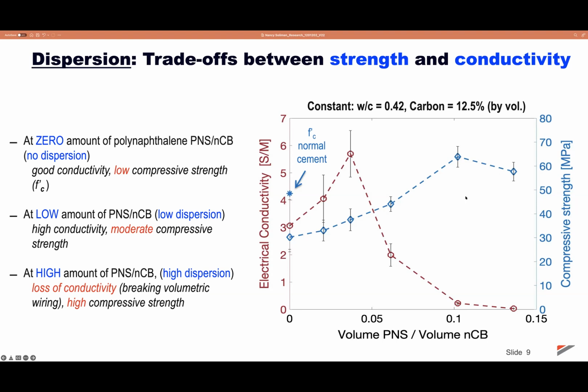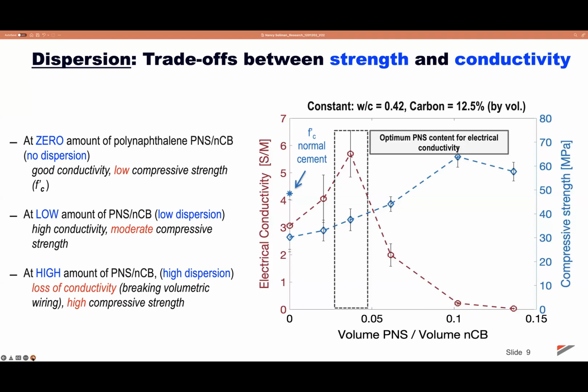And this significant enhancement in the strength is due to the carbon being distributed all over the matrix, which leads to enhanced mechanical properties, while we lose the conductivity due to the breaking of the volumetric wiring of nanocarbon black particles. And because our goal is to achieve an electrically conductive material, we recommend 4% of polynaphthalene superplasticizer as the optimum percentage for dispersing carbon in the cement matrix.